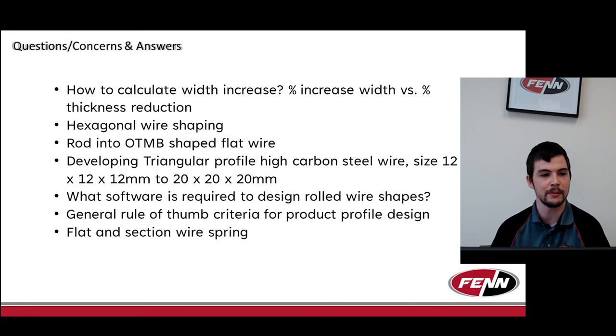Now, I say roughly because, like I said, that first pass, you can get a lot more, especially with materials like copper. So for 8-to-1 on copper, I probably could do that with 2 stands. If you said, I want to do 8-to-1 on spring steel, you might be pushing the limit on 2 stands. Usually on that first stand I can get 3, maybe a little bit more, and then I'm basically doubling it every time after that. So for guys that want to do like 20-to-1, I might get 3-to-1 on the first stand, increase it to roughly 6-to-1, increase it to 12-to-1, use a 4th stand to get it to like 23-to-1-ish, and then come in with a Turk's head or edger to knock it back down to that 20-to-1 ratio, just as a quick example.